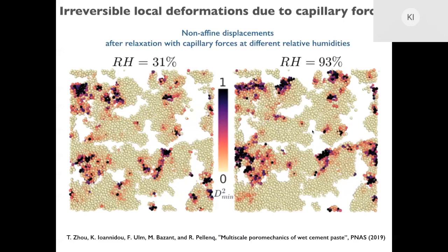From these maps we see that there are a lot of these events, but at the moment they are not percolating in a way that forms a crack. Of course, those were simulations where we were relaxing the structure with no extra load. An interesting thing that we want to explore in the future is what happens if we also have a load, because of course in real conditions on cement there is always some load. It will be interesting to see if these isolated local events will form a percolative path through the structure and create a crack.